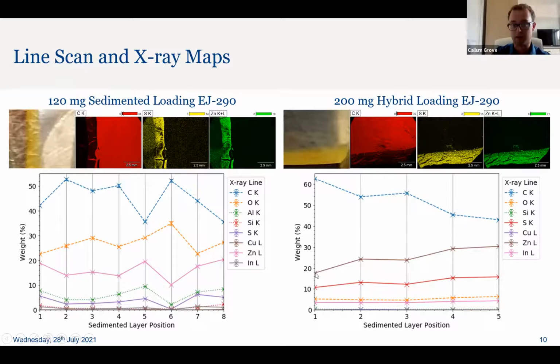And in fact, the percentage loading increased as you went from left to right across the sample, which, as you can see, is consistent with the sedimented layer itself increasing in thickness. What happened was the mold within the casting was slightly tilted forward, which we didn't realize to start with, and so a lot of the quantum dots tried to coalesce towards one side of the sedimented layer. So we ended up with a thicker and more concentrated right region here.